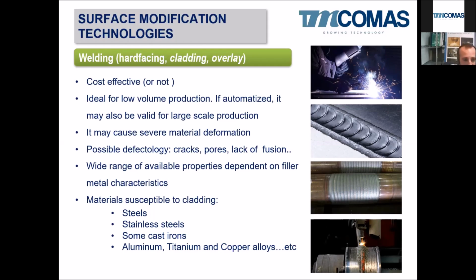So these surface modification technologies, electrode, MIG, TIG, submerged arc welding, electron beam welding, are quite cost effective, or not, depending on if it's very special. But in general, welding is quite cost effective. It's ideal for low volume production. It's clear that if it's automatized, it also can be for large scale production by robotic welding, for example, or heavy duty submerged arc welding. It can cause severe material deformation. All of us know that because of the high heat input of the welding into the material, it can deform it a lot.